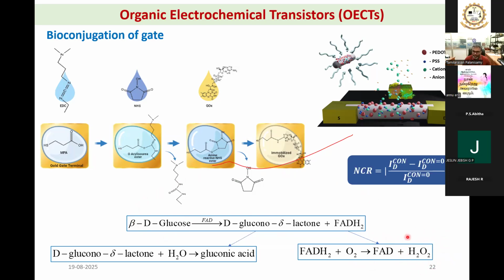This H2O2 molecule is going to make you sensing the glucose because it is proportional to the glucose concentration. When you add H2O2, the gold electrode surface potential will change. And we have a proof for that in the subsequent slide. I'll show you. So the concentration of H2O2 will change the surface potential of this gate electrode. If the surface potential is changed, obviously the degree of modulation will change and the channel conductivity will change. And this is the basic sensing mechanism.